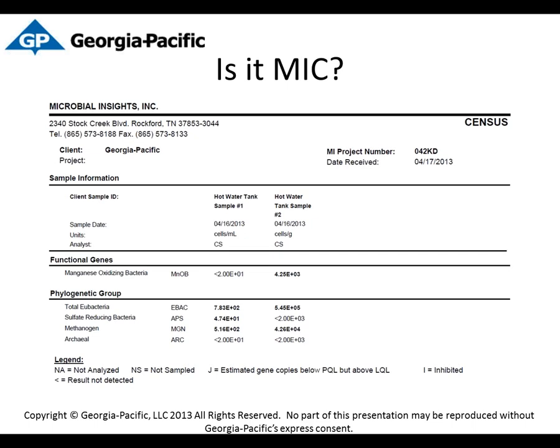So we sent those samples to Dora, actually sent 2 samples. And it's kind of ironic that the water right above the tubercles, the water still sitting in the bottom of the tank, tested differently from the tubercles. Didn't expect that one. But we found in the tubercles manganese oxidizing bacteria. In the water, we found traces of sulfate-reducing bacteria and methanogen. But in the actual colonies, it was mostly methanogen and manganese oxidizing bacteria.